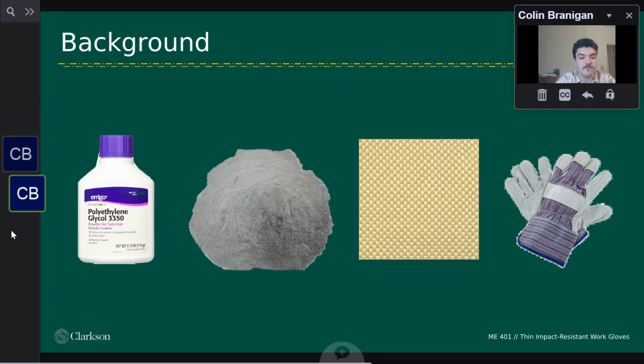The objective was to test several material variations to find the optimal configuration to resist damage. We made our material samples using Kevlar fabric, 1200 grit silicon carbide powder, polyethylene glycol 3350, and ethanol. The silicon carbide powder, polyethylene glycol, and ethanol were mixed in different ratios to produce various shear thickening fluids, or STFs. These non-Newtonian fluids increase in viscosity when exposed to shear stress, improving the impact and puncture resistance while remaining dexterous under normal usage. The technology has been applied to body armor in the past and has the potential for use in other fields. We used each STF variation to saturate the Kevlar sheets to make sample materials. We then tested these materials in a puncture test to determine the forces at which they failed.